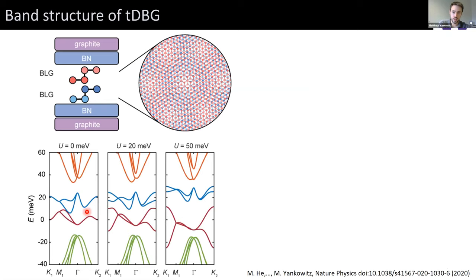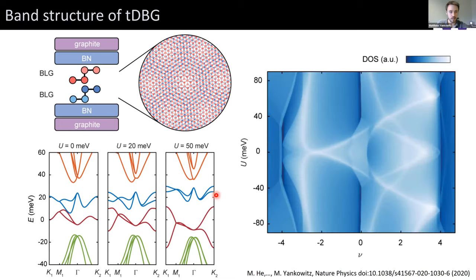About a year after the twisted bilayer graphene discovery, several groups looked at twisted double bilayer graphene and found correlated insulating states at half and quarter fillings, which can be tuned by a displacement field — giving additional control. Curious features were also observed just away from these correlated states: the resistance would drop precipitously to a very small value, sometimes zero, at fairly high temperature around 6 to 10 Kelvin, with potential signatures of spin-triplet pairing if this were truly a superconducting state. We construct structures of bilayer-bilayer graphene at just over one degree. The band structure shows a band-overlap semi-metal at small electric field which opens a gap between the moiré conduction and valence bands as electric field is applied — the full calculation shows density of states gaps at full filling and the neutrality point, plus Van Hove singularities drifting around different fillings.